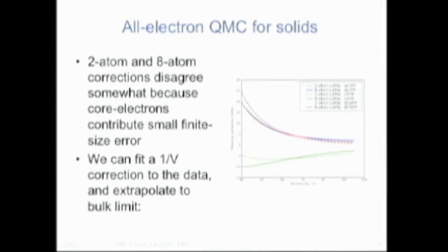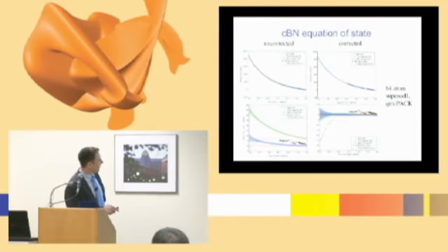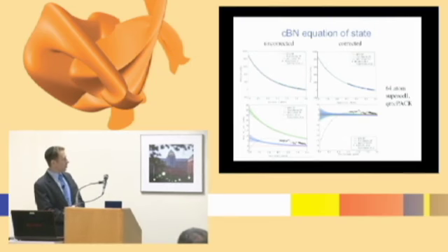So what we found, let's see, I'll just go to here. If you plot them just as pressure versus volume, it seems like everything agrees, okay? But the problem is, the importance is in the differences. So if you plot the difference from this general curve here, you get this. And you see that different pseudopotentials, represented by these different colored bands, gave very different results, whereas the experiments were shown here as the point.